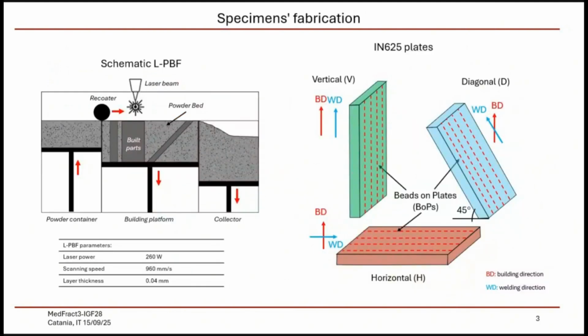So as I said, we work on IN625 in this project. This is one of the easier to weld nickel-based superalloys because it's a solid solution strengthened alloy. And in this case, we work with these 3 plates produced by laser powder bed fusion, which is a well-established process. I assume you are already familiar with the process. You can see the main process parameters in the table.